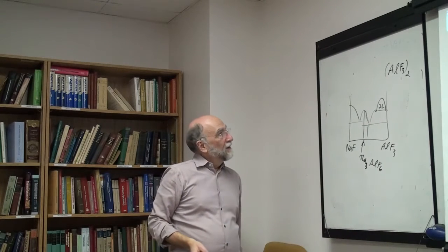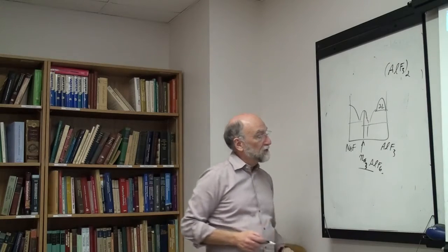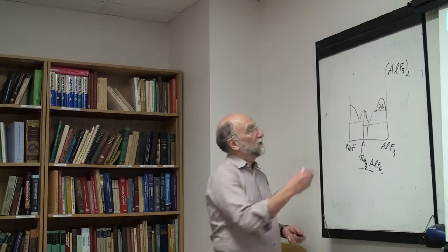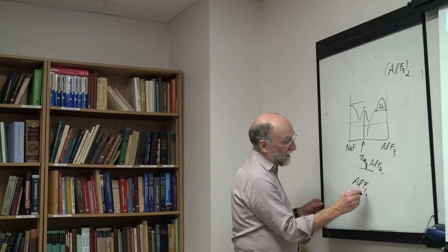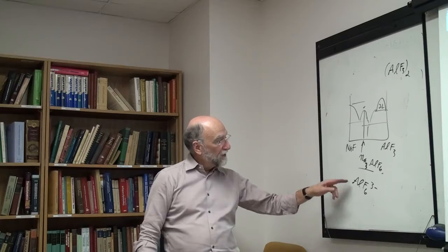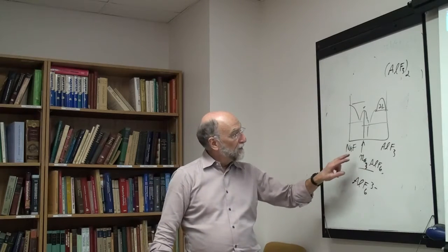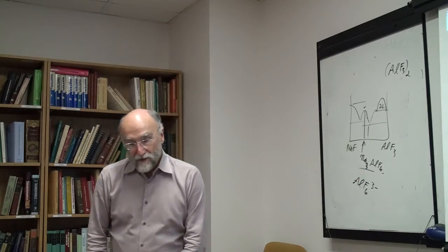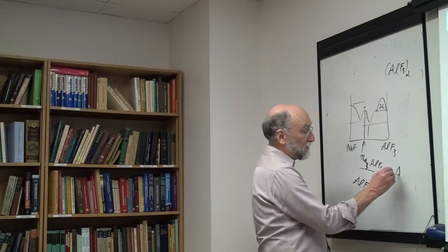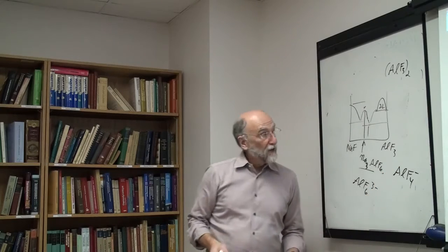Okay. And this led everybody to believe, since you do have an actual solid compound, solid cryolite, in your electrolyte region over here, to presume that in the liquid you had AlF6 complexes. Or in the quasi-chemical model, the ratio of Z would be 3 to 1. But when you really look at all the liquid data, the enthalpies, the activities, and all these things, there really is very little evidence for complexing around AlF6 composition. The complexing seems to be around the AlF4 in the liquid, even though there's a solid compound.